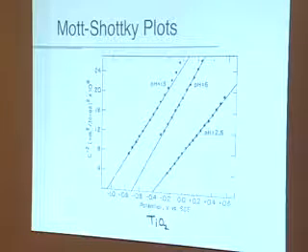You will notice that in the case of TiO2 this band edge is pH sensitive. It's just 60 millivolts approximately per pH unit, which has to do with protonation and deprotonation of the metal oxide surface here. According to the Mott-Schottky equation, all these lines are parallel to each other because they depend on the semiconductor dopant concentration. You can see there's a little problem there, but we won't get into that today.